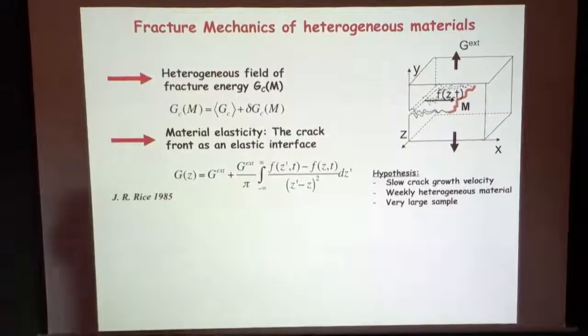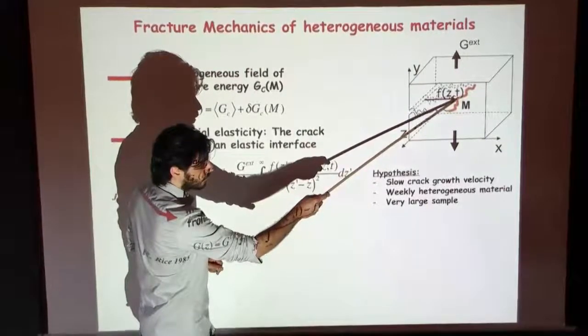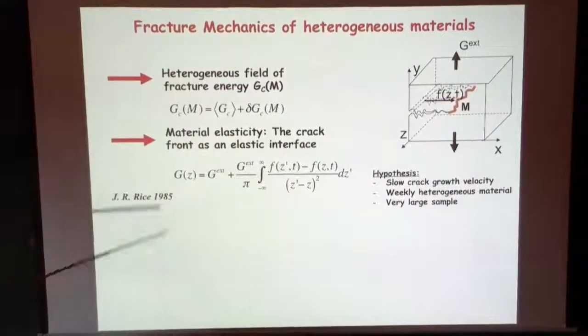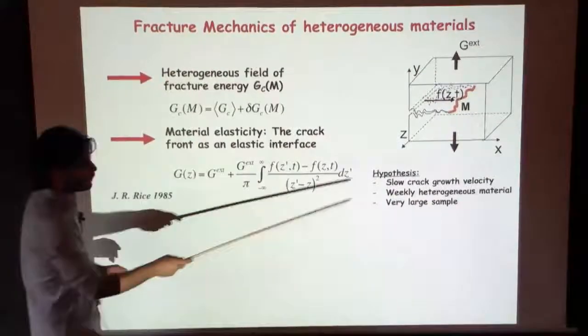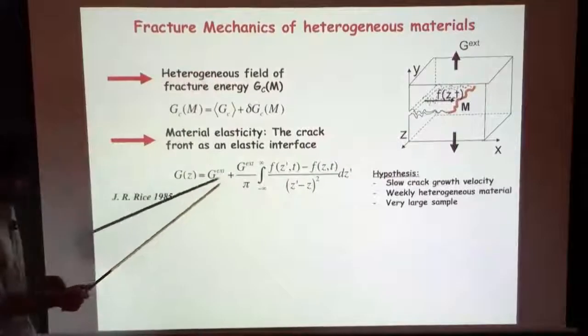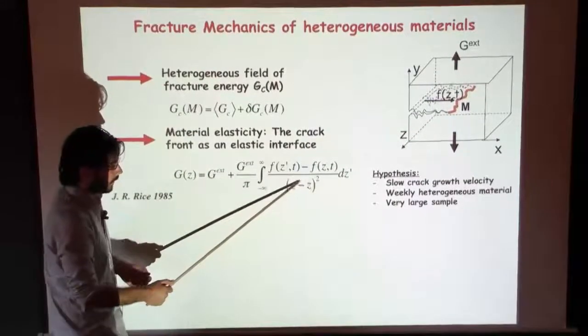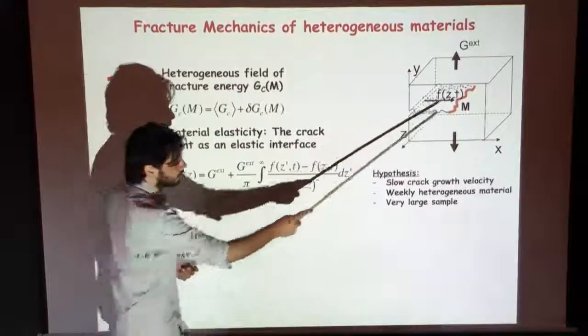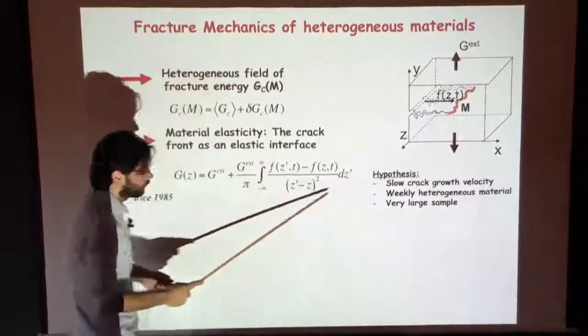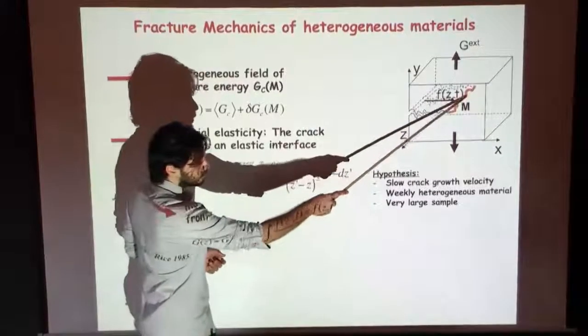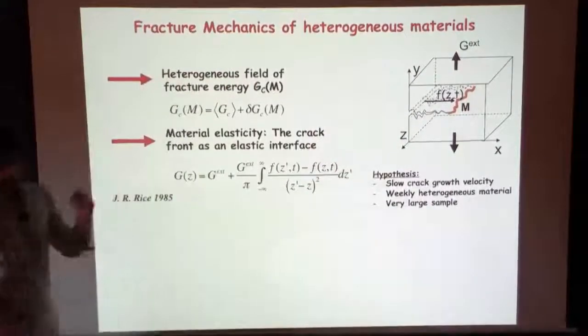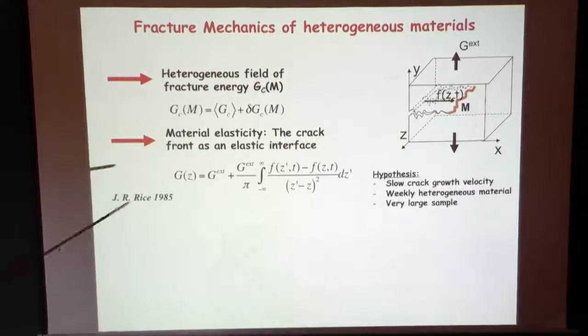Under this specific condition, you can have an analytical expression for the driving force at some point as a function of the geometry of your front. This is the expression. You calculate this through development of the stress field using perturbed boundary conditions, and it is written as a constant term plus a perturbation. That is a non-local perturbation, telling you that the value of the driving force here depends on the full geometry of the front, and also we have a minus f here, telling you that if the front is late, the driving force is slightly larger than the average driving force G, and if the front is in advance, the driving force is slightly smaller. So that's why I call it a pseudo-line elasticity. The distribution of driving force along the front tries to maintain the front straight, okay?